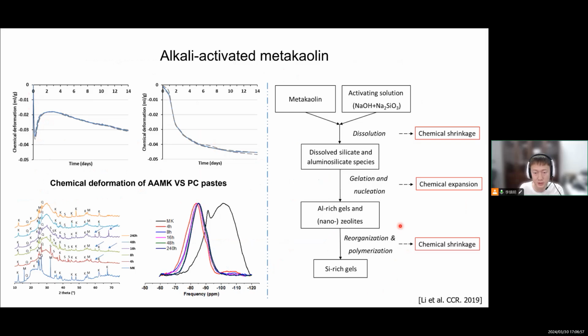As we found in the literature, the gel polymerization or alkali activation can be divided into 3 stages, and I correlate these stages with the deformations. In the first stage, it is basically the dissolution of the precursors, and because the volume of the ions after dissolution is smaller than the volume it occupies as a solid, there will be chemical shrinkage during this dissolution stage. And during the formation of alumina-rich gels, which we can clearly see from the NMR results, there will be chemical expansion, which means the total volume actually increases.